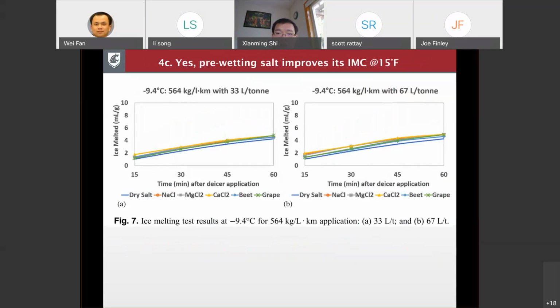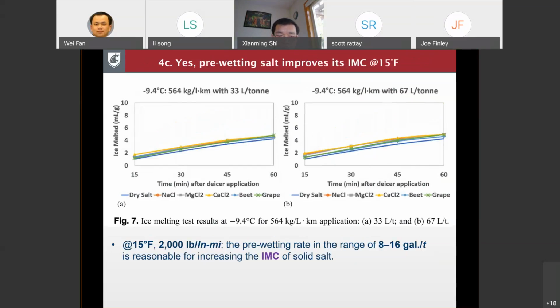Now, what about a colder temperature, 15 degrees? In this case, we further bumped up the application rate of pre-wet salt, and you're still seeing the benefits. Well, actually, I forgot to mention, on the left-hand side, we're talking about 8 gallon per ton pre-wet rate. On the right-hand side is 16 gallon per ton.